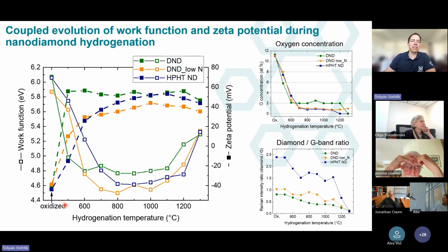And what is interesting is that these low nitrogen nanodiamonds develop the zeta potential slower, let's say. So they need the higher hydrogenation temperature, and in both cases we see some maximum of the zeta potential, which is at 1000 for low nitrogen DND and 1100 for the HPHT nanodiamond. And this is exactly just before the severe graphitization occurs. So this graph tells that not only the hydrogen termination is important to achieve the positive zeta potential, but its magnitude is also somehow associated with the surface structure and quite probably with the formation of this disordered sp2-like surface carbon content, which is highest just before the excessive graphitization.